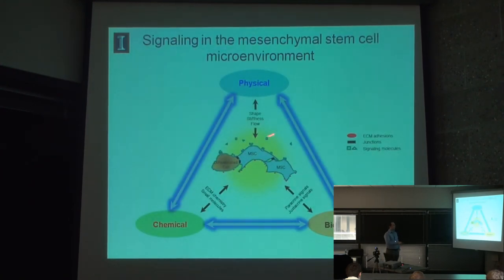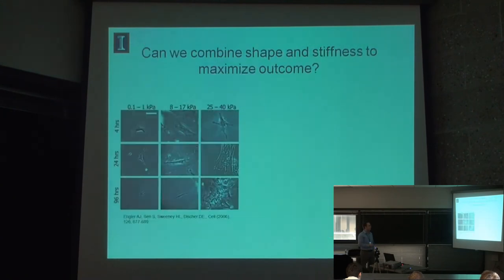We can now vary things like shape and stiffness. We can also look at variations in ECM chemistry and stiffness and shape. And so my lab's actively looking at ways that we can develop platforms to vary these things rationally and controllably. And shape and stiffness, I got excited about this. Here's the work by Engler and Discher again, where we see very different shapes across these different stiffness gels. Here's a neuron, myoblast, and osteoblast. But when I did these experiments, I saw a mixture of things.